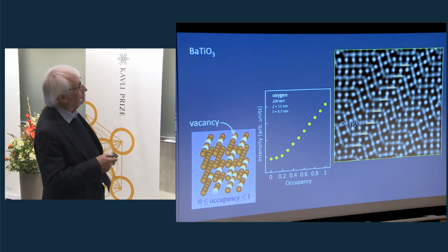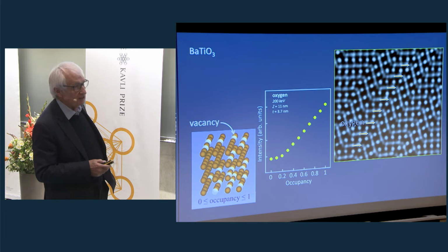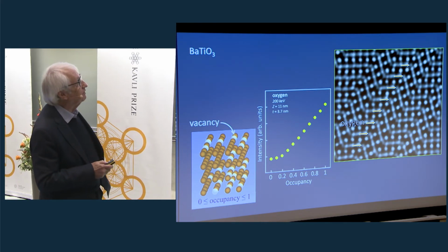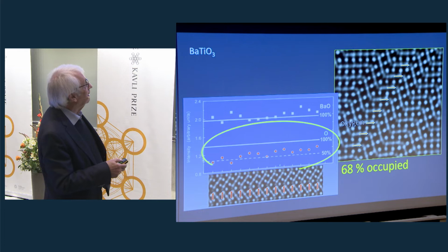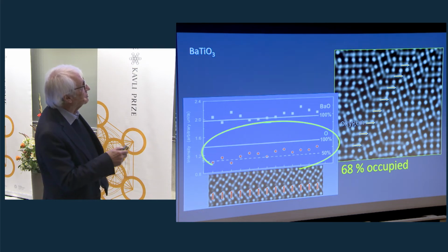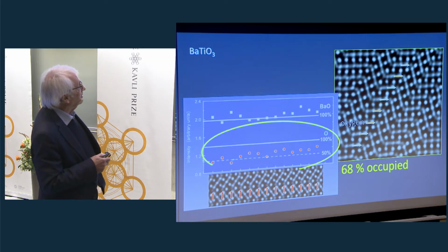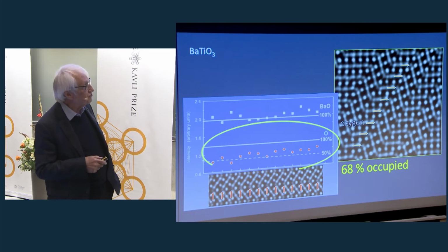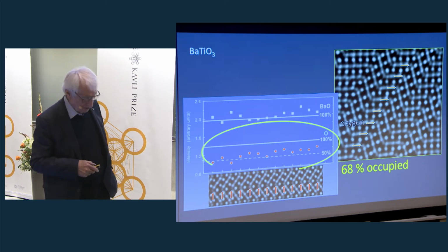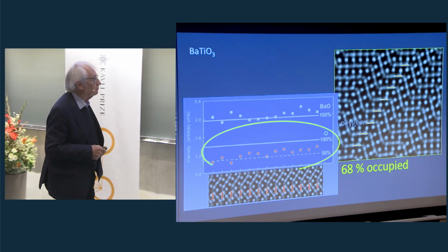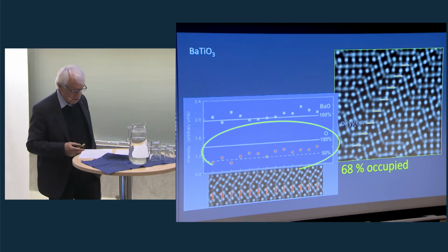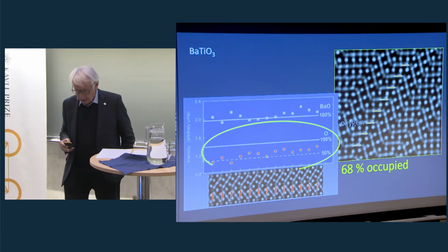And this then we compared with the quantitative measurements in the images, and here we have the oxygen results. This is for barium as a control test, and this would be 100% oxygen, and here we have 50%, and you see that the concentration of oxygen is reduced. Only 68% of the oxygen sites are occupied, 32% of them are left vacant.